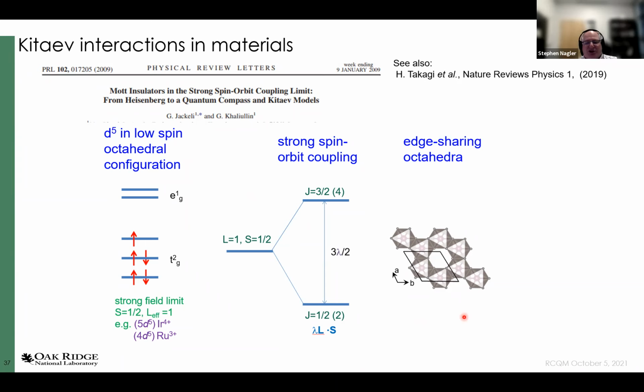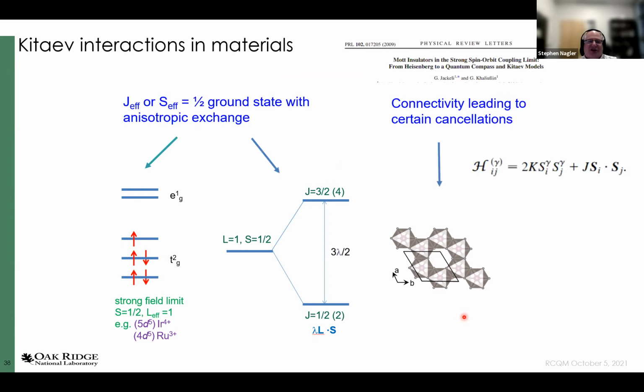And now comes the other ingredient that's important, edge sharing octahedra. And with that particular geometry, they could show that in fact you have anisotropic exchange, but the connectivity leads to some cancellations of what would normally be sort of J.J exchange here, so that what's left over is a Kitaev term that, along each axis, well, I'll get back to the axes in a second, a Kitaev term that's different along 3 different axes, and a Heisenberg term.